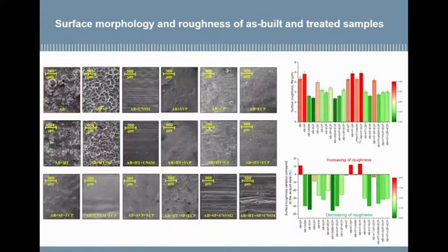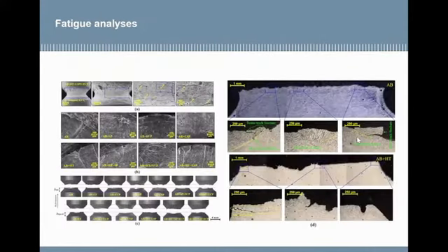So depending on the treatment, of course, the chemical treatments are much more efficient in smoothing the surface, but even shot peening, although it is not known as a treatment to reduce surface roughness, was reducing the surface roughness considerably compared to the as-built case, because it was eliminating these partially melted powders that were randomly distributed on the surface. And then finally, the fatigue test.